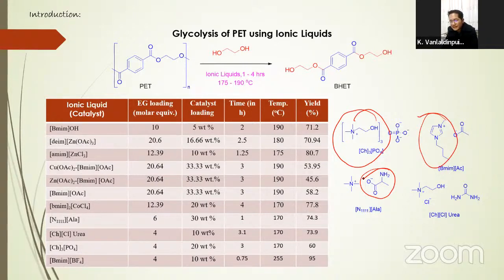So many different types of ionic liquids were employed for these transformations, and here I have given some examples. If you look at entry number 1, BIM-OH, this is 1-butyl-3-methyl imidazolium hydroxide. So using that and using 10 equivalents of ethylene glycol at a catalyst loading of 5%, the reaction takes 2 hours to complete at 190 degrees Celsius, giving 71% yield.